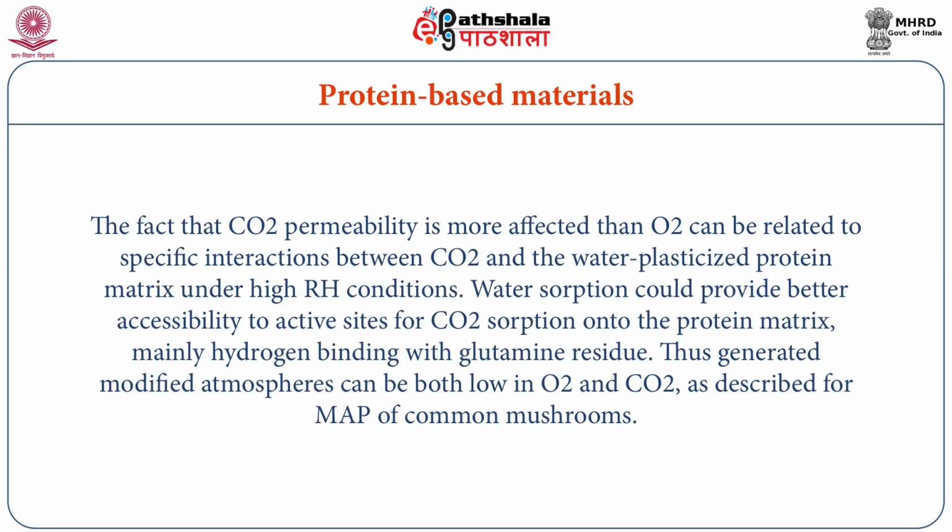The fact that carbon dioxide permeability is more affected than oxygen can be related to specific interaction between carbon dioxide and the water plasticized protein matrix under high RH conditions.